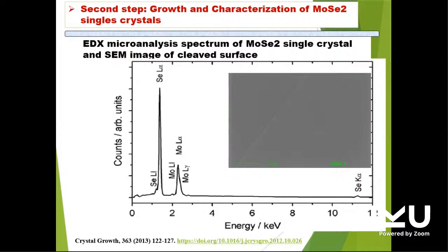EDX analysis coupled with SEM spectra show that the material is not contaminated by the grow process. The spectrum only shows selenium and molybdenum peaks. So we can see that they are not contaminated.